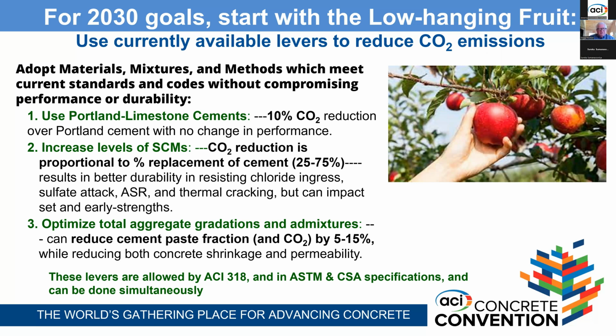And one that only gets mixed results, though it has great results, but it's not being used very effectively in North America, is optimizing total aggregate gradations. You can reduce the cement paste fraction by better packing of the aggregates, which typically need at least 3 size ranges of aggregates combined to optimize. You can significantly reduce the amount of cement paste you need in the mix by about 5 to 15%. At the same time, you get reduced shrinkage and reduced concrete permeability, because the shrinkage and permeability are taking place in the paste fraction. So if you reduce the paste fraction, you're going to reduce that. And of course, chemical admixtures allow us to do that while maintaining the required workability for placement.